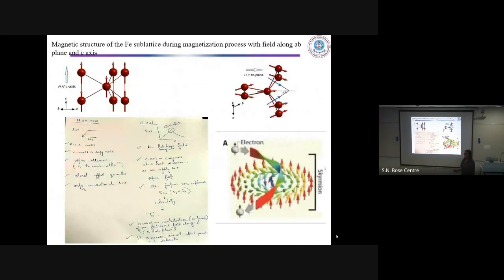Yeah, this one. So if you consider the magnetic structure of the iron sublattice, when the magnetic field is applied parallel to the c-axis, which is the easy axis, the spins are collinear to each other and we don't have any chirality. But when the magnetic field is applied perpendicular to the c-axis, or parallel to the AB plane, since c-axis is the easy axis and the AB direction is the hard direction, as we apply the magnetic field there is a spin flop happening. But this system also has a large magnetic anisotropy. So this competition gives rise to a non-coplanar structure, with a Si cross Sj term, which gives rise to the chirality, and you have the existence of this kind of texture in this Fe3GeTe2 system.